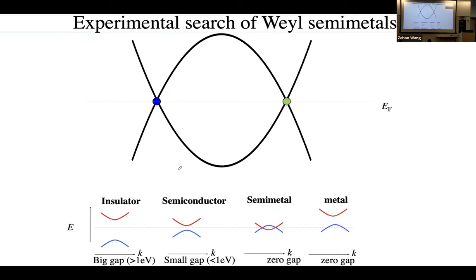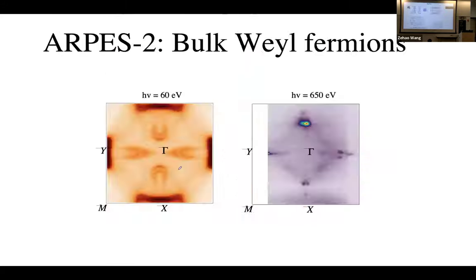The key idea: think about sodium chloride. In the molecular limit, the HOMO and LUMO are the cation and anion states, with an energy gap proportional to ionic bonding strength — the energy for sodium to reclaim its donated electron. The second energy scale is the hopping amplitude, describing wavefunction overlap between neighboring orbitals. For NaCl the electronegativity difference is large, so even after forming a band, you still have an insulator. For a Weyl semimetal candidate, we need an AB-type compound where the electronegativity difference is much smaller, so the bands cross.